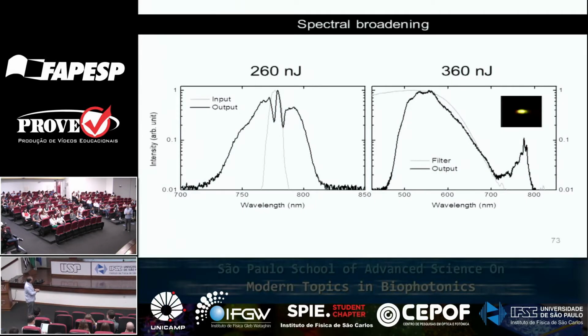So that's the spectrum. You barely see the gray line. The gray line here, I'm just indicating, is the spectrum of the pump laser. And then, because of an effect related to self-phase modulation, in the output, you get a very broad band. So you see here, it goes from 800 all the way to 500 nanometers, and I actually have a filter to block some part of the light in this part here. But anyways, it goes from 500 all the way to 800 nanometers. It gives this kind of white color coming out.